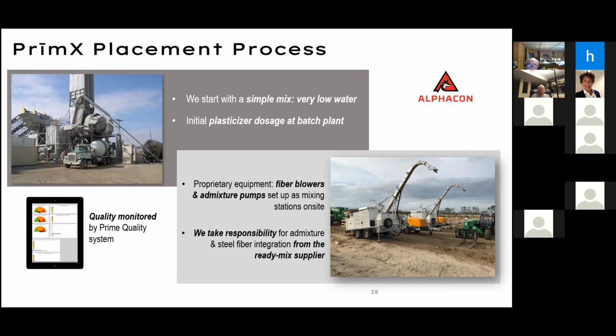It is becoming improved by blowing the fibers at very high speeds inside the truck. The truck is the worst mixer in the world. I always say this because there's no energy to mix at all, unlike your kitchen blender. But it puts the materials in that truck in movement. That means that if you are blowing fibers at the back of the truck, every little element of volume of concrete will see incremental fiber additions over time because the truck moves those materials very well. It doesn't mix them well, but it moves them very well. So that is not enough. We have to use a cementitious additive, which is then hydrated on site in a known dosing fashion. That proprietary additive is what is going to secure performance in an excess water situation, just as Kevin mentioned earlier.